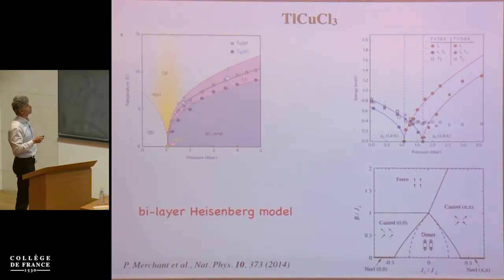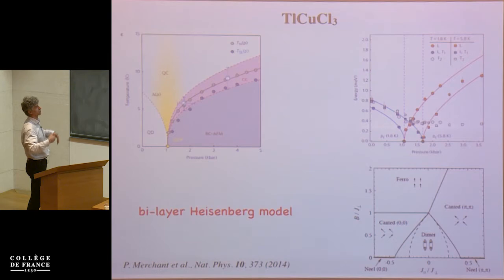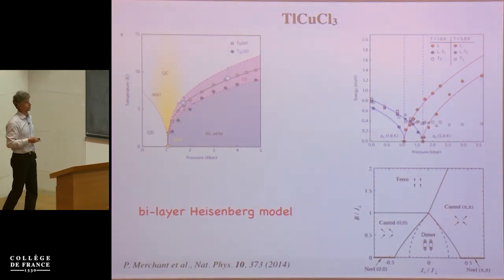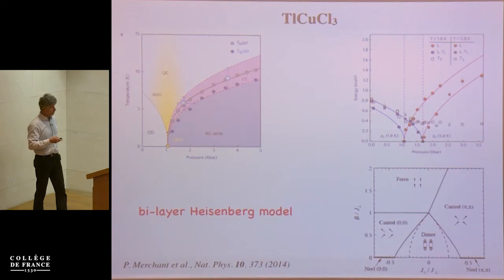And this can be tuned with rather small pressure in this material, and so these are experimental studies of the magnetic collective mode, which come from this work of Merchant and collaborators.